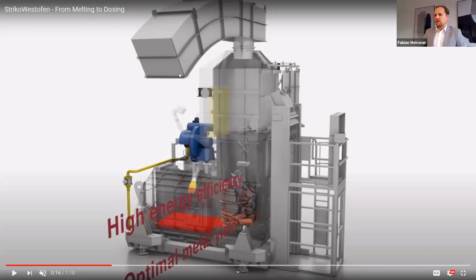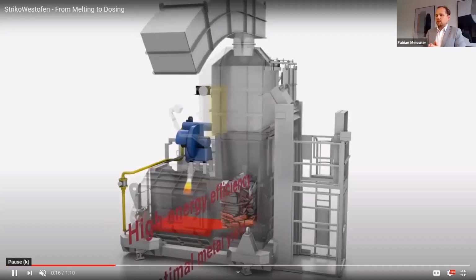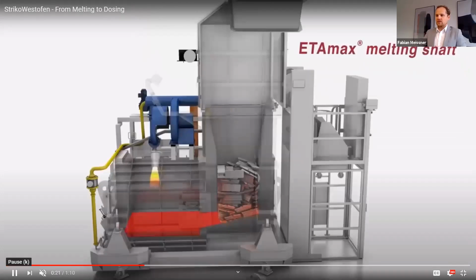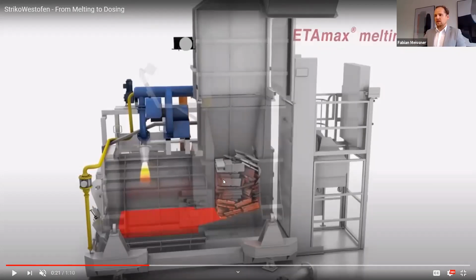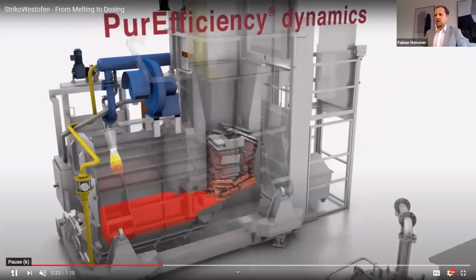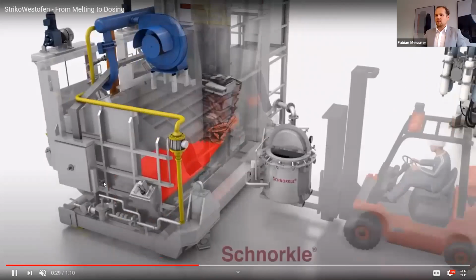And you can see a tiltable version. If you want to tap out or take out the metal, you can move it, in this case now to you, and then it takes out the metal from the furnace. Or we have another version, a tap version or tapping version, where you have an automatic or semi-automatic valve, which you can use to take out the metal. There are these two major versions. Yeah, you can see it's charged now, and now the preheating of the material is done. So you can see the combustion air, due to some under pressure, is going into the shaft, using the heat to preheat the material, and it's slowly melting down and going into the holding bath of the furnace.